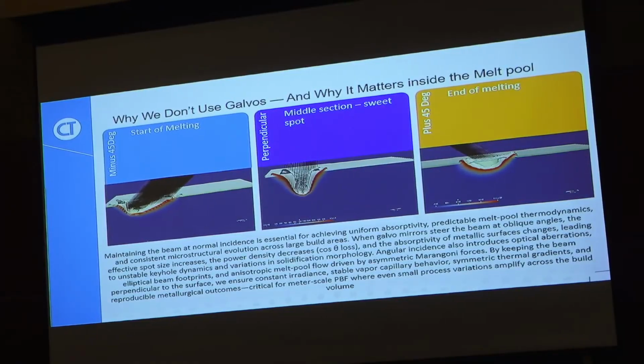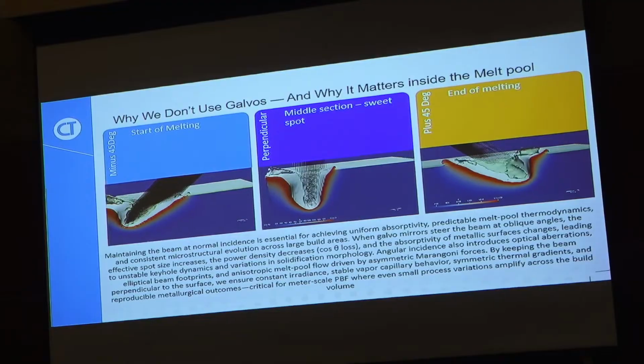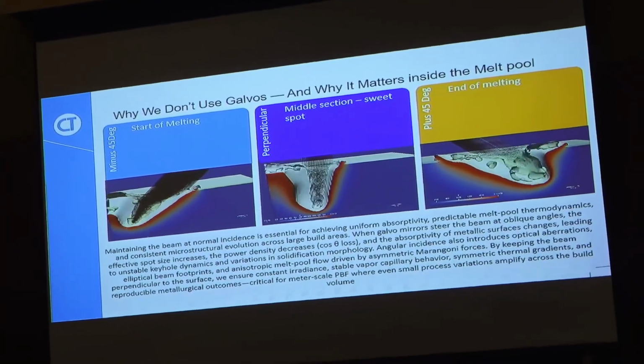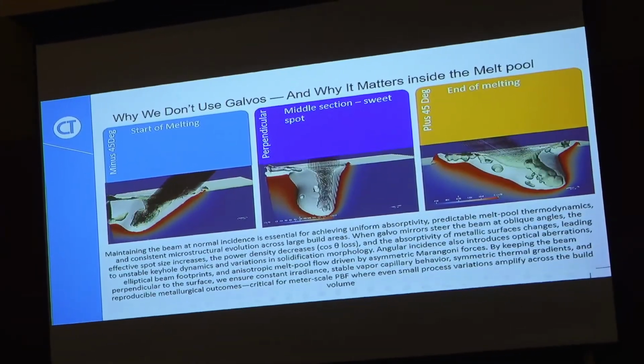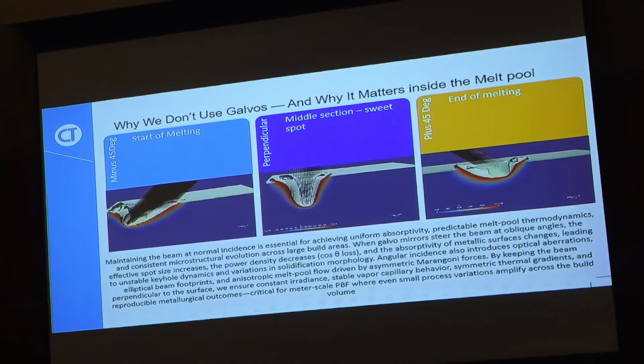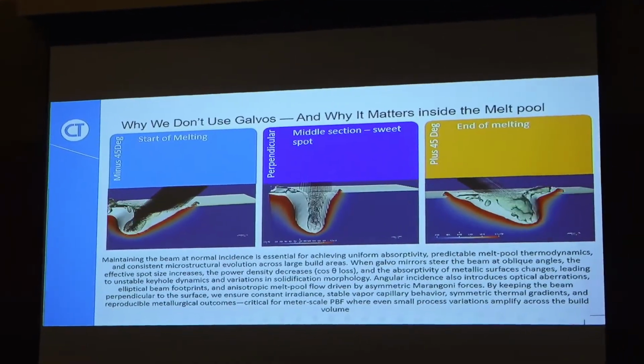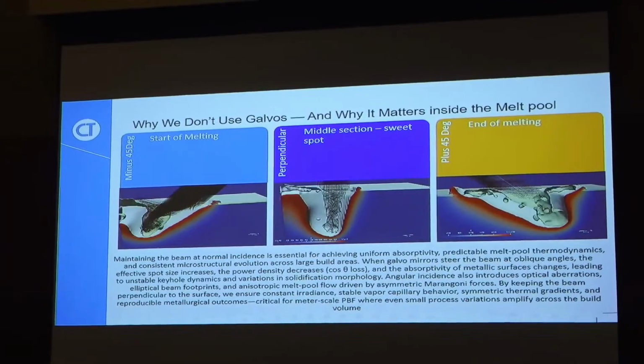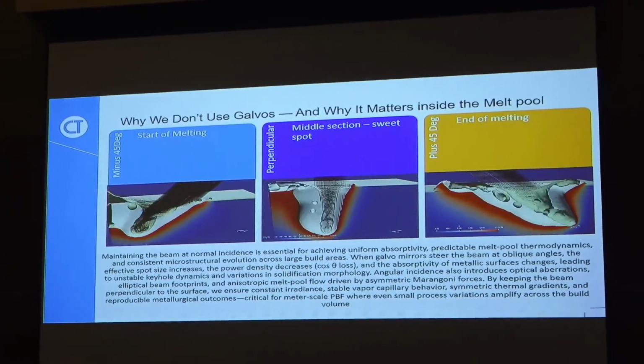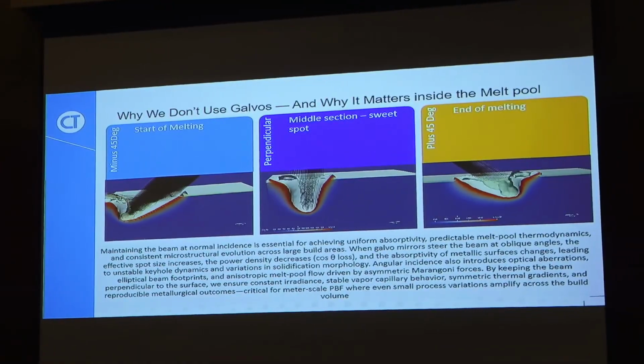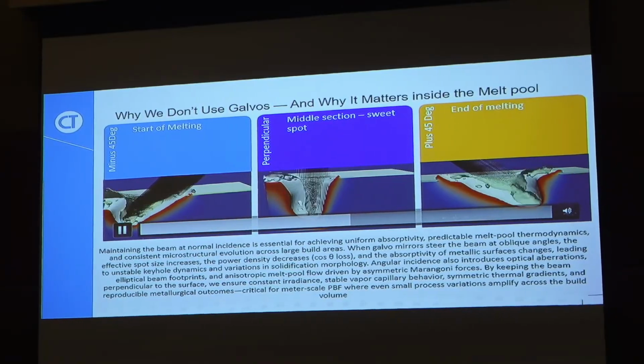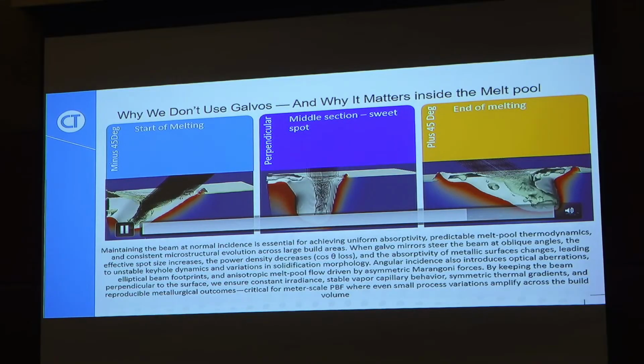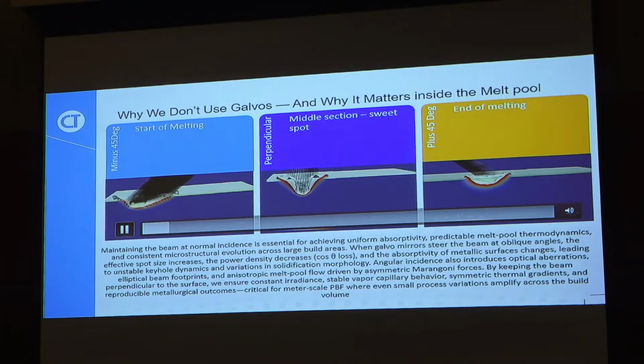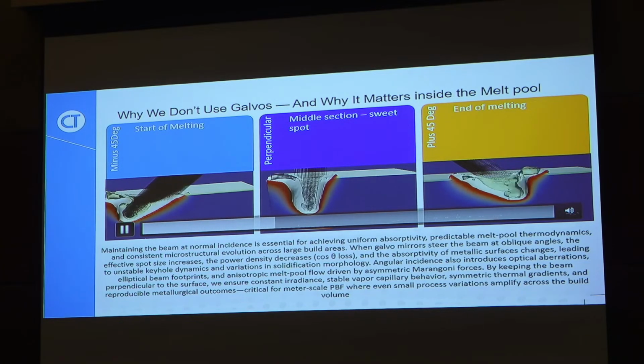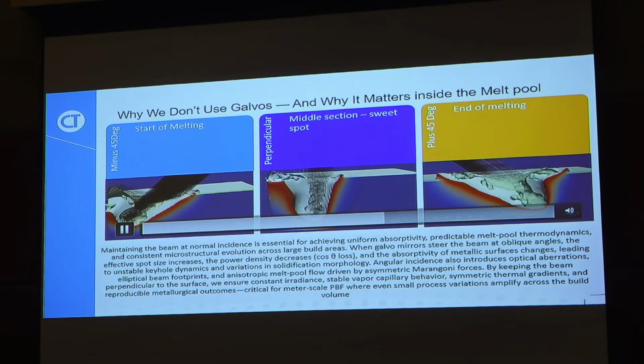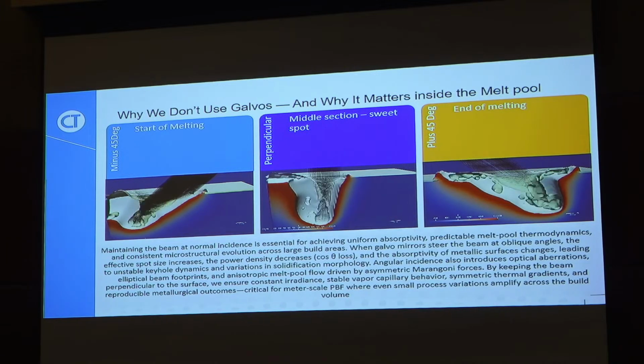So the reason why we do that is these 3 simulations are now showing the galvo approach, right? So the left is a CFD model of the beam when it starts. So let's say we start in one position, then we move over the area with the other position. You can see that the heat profile in the heat affected zone is totally different, and the sweet spot, how this thing is actually melting the powder, is different from the vertical or the end position. You can see when you actually make bended melt pools in one direction, vertical, and you cut them and you look at them in the cross section, they look completely different, okay? So now imagine you're printing a large component and you're using galvos and you hope that you get the same conditions. It's impossible, okay? You can correct the focal point, but you cannot correct the melt pool because the beam is still at an angle. So we said, okay, our goal is we want to be vertical.